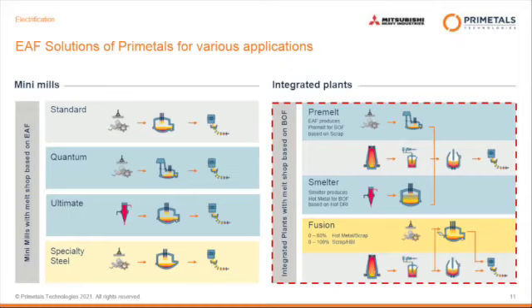So we will see a broad range of technologies, either for mini mills, but also for hybrid mills when it comes to electrification. On the left side, the mini mills with standard furnaces, preheating furnaces that allow preheating of the scrap, and high-powered electric arc furnaces that use a high share of DRI with hot feed. And on the right-hand side, various solutions to be integrated in integrated plants. So melting technologies to provide hot metal, to replace hot metal from the blast furnace, but also smelting technologies for low-grade DRI, and very flexible furnaces. The branding at Primetals here is a fusion furnace that allows really high material charge flexibility at the end.